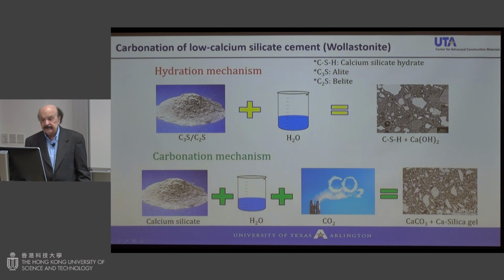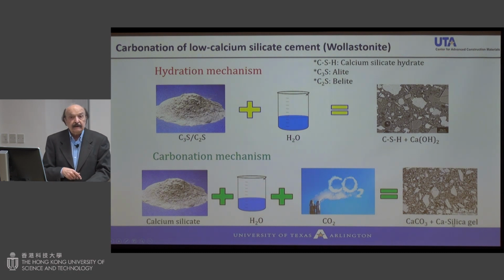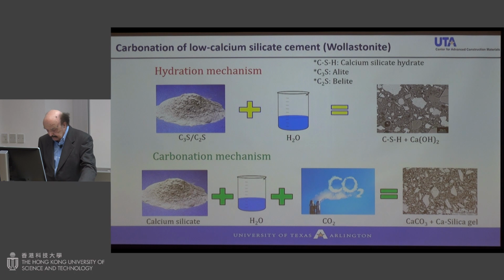But there are two things here. I mean, this is where really the innovations come. One, I mentioned that you can manipulate the polymorph of calcium carbonate. What is also important is that this calcium silica gel can act after carbonation as a pozzolanic material, which I will show you a couple of examples. So that's quite interesting. The strength is given by both calcium carbonate and calcium silica gel, and you can control and manipulate that, and a lot of research needs to be done.